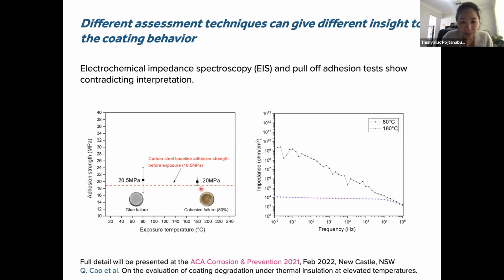At the higher temperature end of the test pipe, at 180 degrees, adhesion strength is still very high, still 20 MPa. Even though the failure mode changed from glue failure to cohesive failure, the adhesion strength is still very high. So usually we will look at the adhesion strength and correlate that with the coating not being affected.